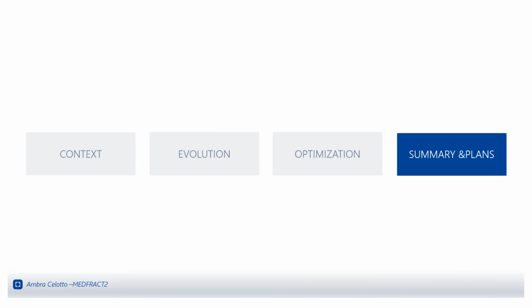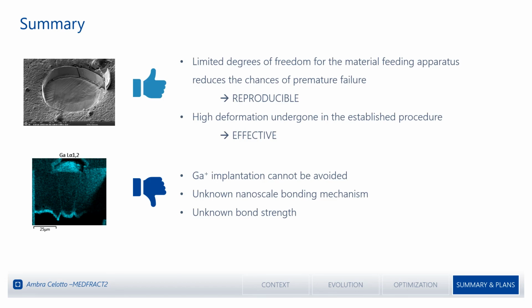Let's have a look now at what we have done in a summary and what we are planning to do. In summary, we can say that first of all, by limiting the degrees of freedom for the filler metal tip while it was being pushed, we were able to have a lower probability of premature failure, and this made the method quite reproducible. And the high plastic deformation that was undergone by both metals, above all in the established procedure, made the method also really effective. But on the other hand, we have to admit that the gallium implantation is an issue that cannot be avoided, and there are some lacks in our knowledge, for example, the nanoscale bonding mechanism, and of course, maybe the most important one, the bond strength and the mechanical properties of the joint.